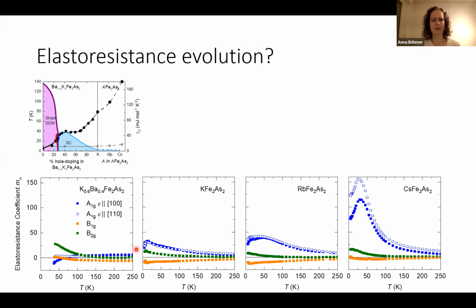We go further, the A1g component starts to grow, the B2g shrinks, and there's a finite B1g. We go further, and we see this growth of the A1g component, the symmetric one. The B2g one, that would be our nematic susceptibility, well, doesn't change very much anymore, it's there.